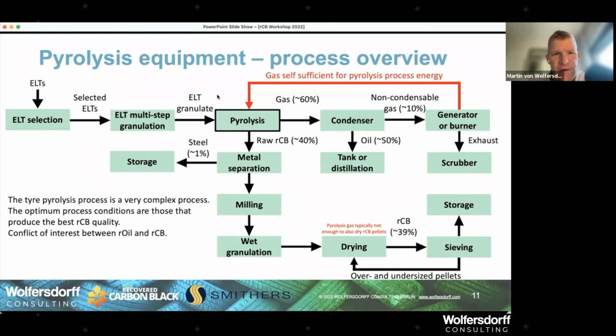It really depends. And then, of course, the question is, which one is better? And that question cannot be answered because it depends on the feedstock. It depends on the geography. It might depend on your budget, what you're willing to spend on the pyrolysis plant. For the recovered carbon black, I don't think it plays a major role. Although I would say the volatile reduction is easier in the batch mode because we can just leave it longer in. A typical batch reactor is anything between 8 and 14 hours, whereas in a continuous reactor, the flow is such that the material has to pass through the reactor. So typically you have maybe 1 hour maximum to spend time for the heating. So your time to heat is much more limited than in the batch kiln. Frederick, I hope that answered your question.